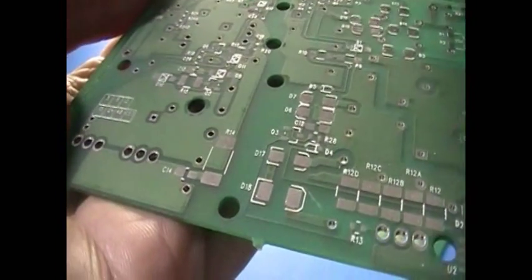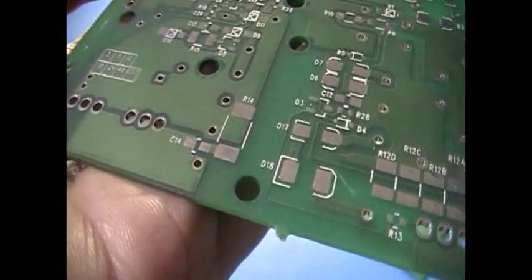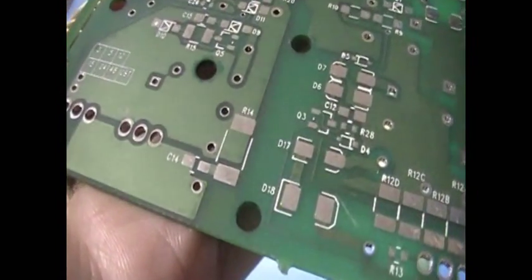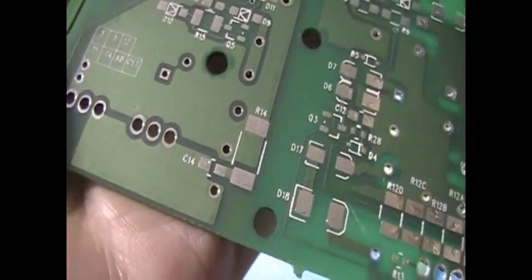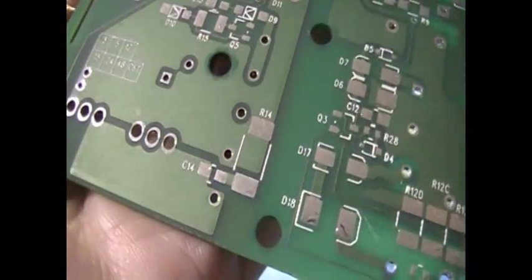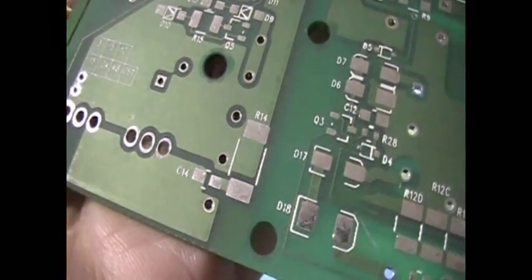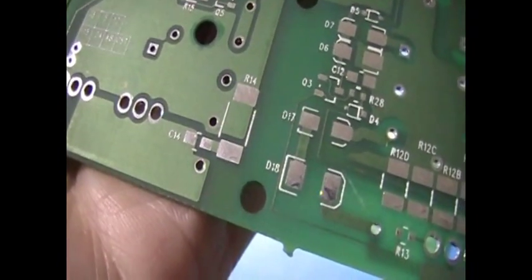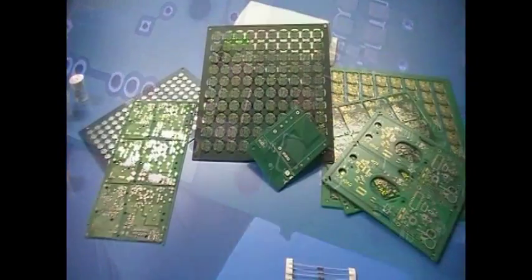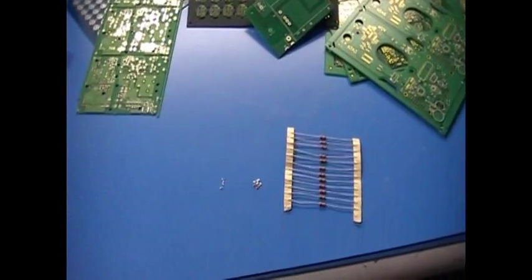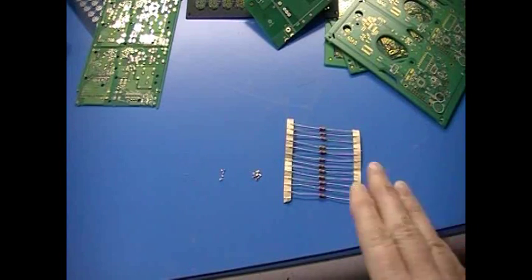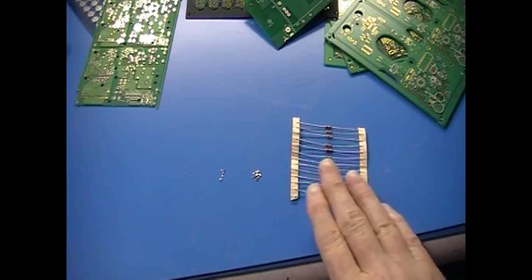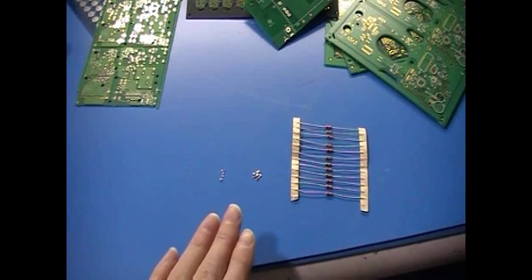But you can see the surface is not perfectly level. This would cause significant solderability issues with small surface mount components. HASL is a good economical choice if you're using through hole or larger SMT components.